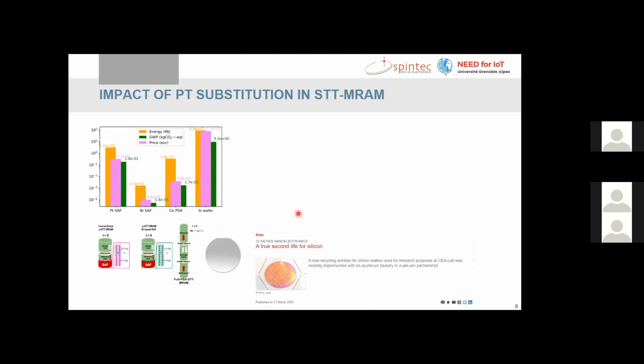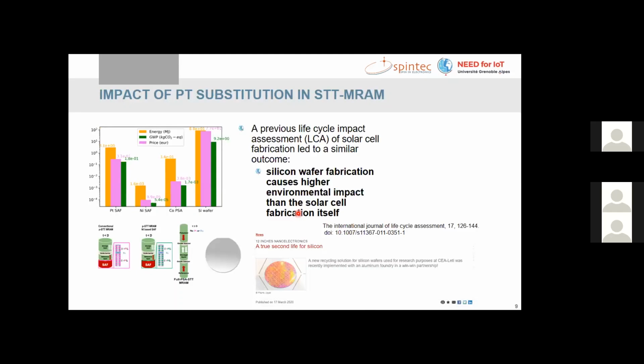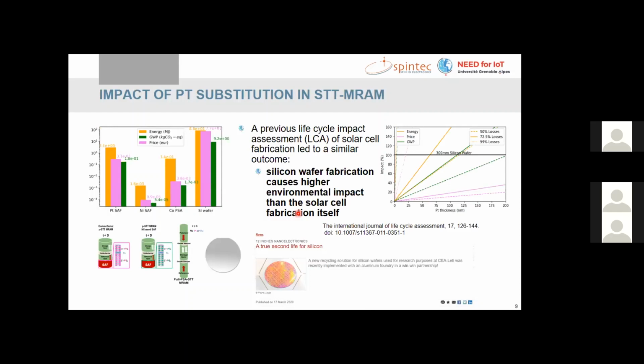Okay, so because of this, initiatives such as the recycling of silicon that we have seen recently in Leti can be important. But well, this I just show so that the platinum thickness that we would have to have in our wafer to have similar impact to the silicon wafer itself would be as high as 50 nanometers. That is not the case for STT-MRAM, where we use only 2.25 nanometers of platinum layer.